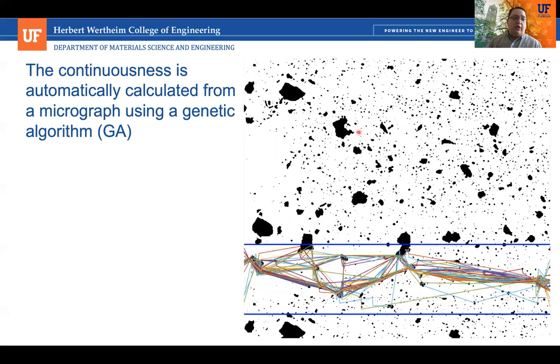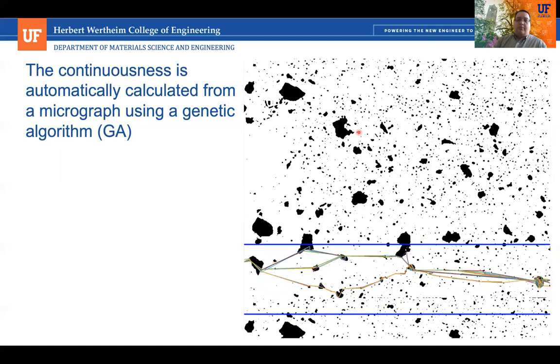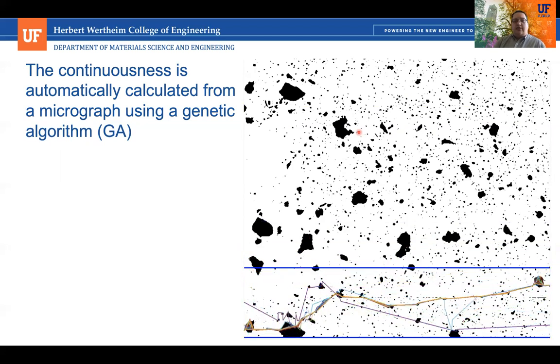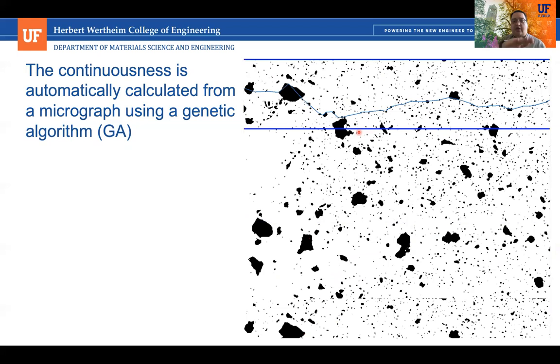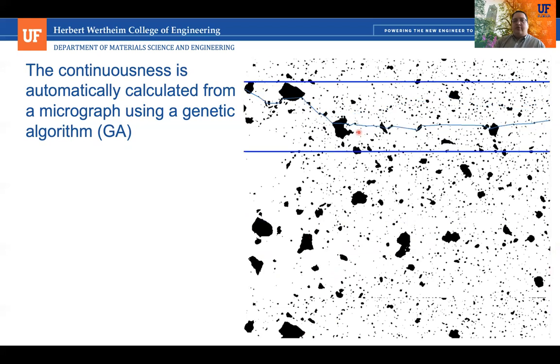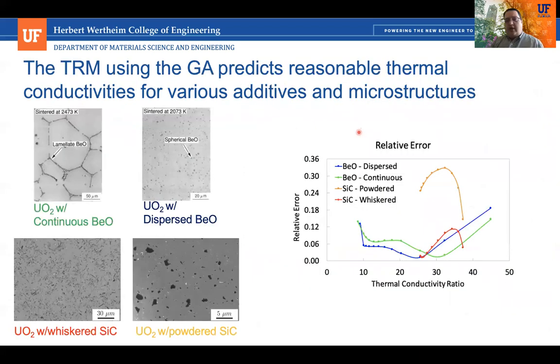And so you just provide the image of your microstructure, and it estimates the additive, and it does it at multiple paths, and then takes an average of those values to get the average continuousness. So we've applied our model to various microstructures from the literature where they've measured the thermal conductivity of their microstructures.